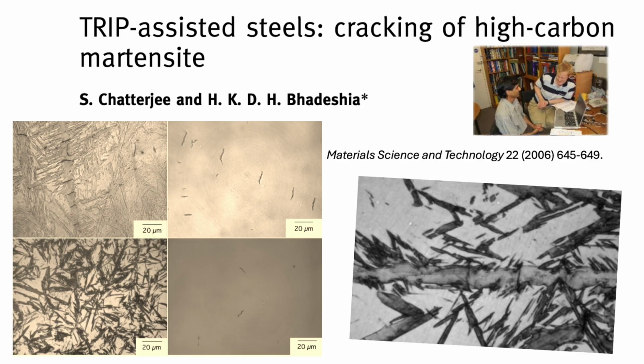Okay, so let's try and summarize the main takeaway here for the listener. How does brittle martensite work in tough TRIP steels? The reason that untempered, hard, high-carbon martensite doesn't just shatter the steel is fundamentally about size. By carefully controlling the process to keep the initial austenite grains fine, engineers ensure that the martensite plates that form are also very fine, likely below that critical 10-micron length. And because they're so small. Because they're so small, the surrounding softer steel matrix simply cannot transfer enough stress onto them to reach their fracture point. They're too short to break easily. It's structural reinforcement at the microscale.